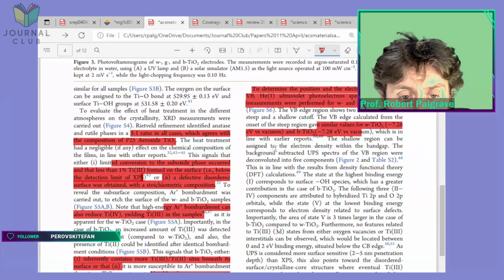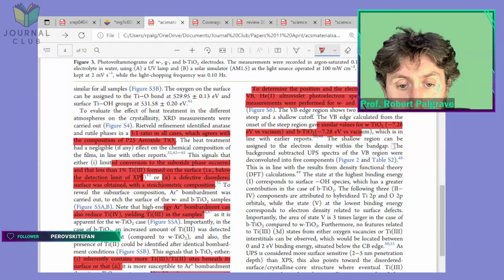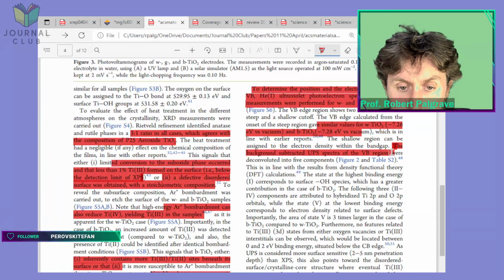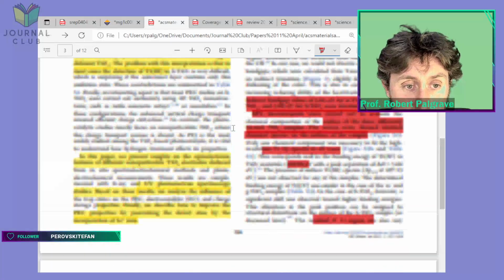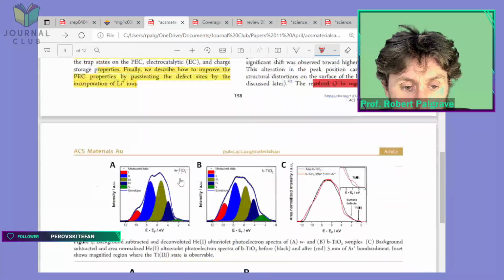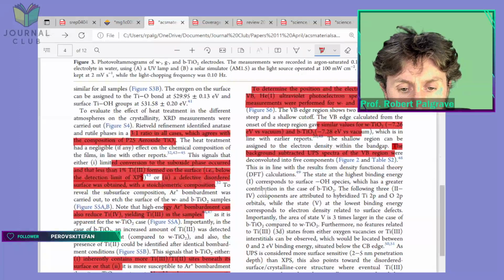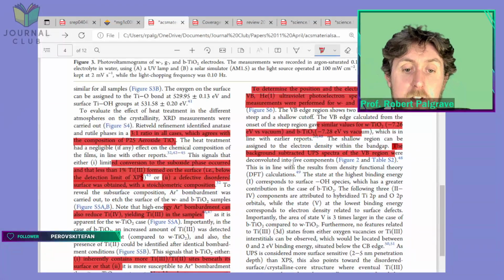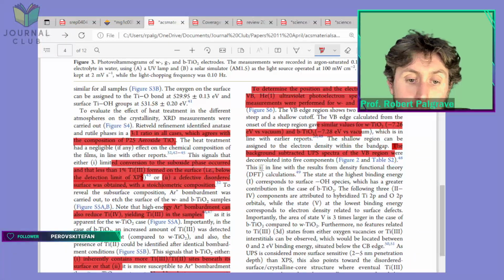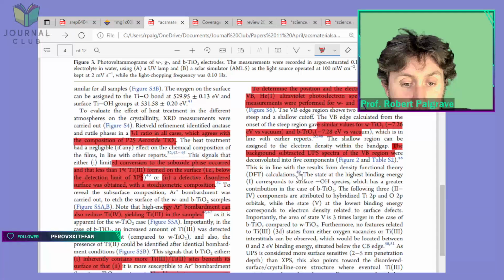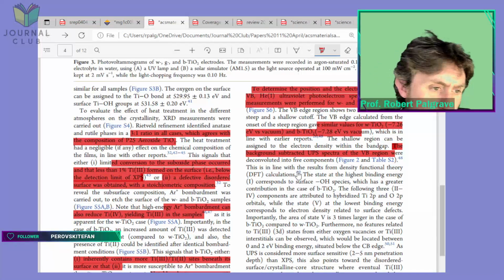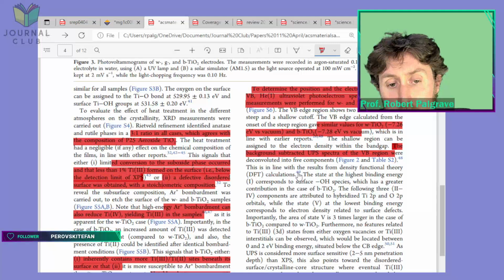So the background subtracted UPS spectra, so that's what I spent probably about 15 minutes explaining. But that's these things up here anyway. That's these spectra here. The background subtracted UPS spectra were deconvoluted into 5 components. This is in line with the results from density functional theory DFT calculation. Okay, I might not have time, I might look up this paper and see what it said.